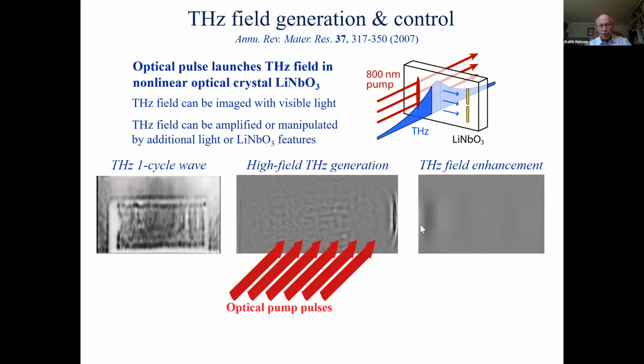as our terahertz source. We can also make the field even stronger in local regions by using little structures like this. This is a little gold dipole antenna, just 2 strips of gold. And what you can see is that when a terahertz field arrives there, the strongest field is produced in a little micron gap in between the strips. Right there, you can see by eye that the brightest place is right there. And that's happening because the terahertz field is moving electrons away from the gap in one side toward it another. So there's a big field that's generated right there at the gap, stronger than the terahertz field that induced it in the first place.